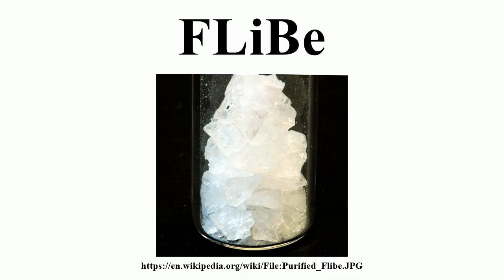This moisture plays a negative role at high temperature by converting BeF2, and to a lesser extent LiF, into an oxide or hydroxide through the reactions. And, while BeF2 is a very stable chemical compound, the formation of oxides, hydroxides, and hydrogen fluoride reduce the stability and inertness of the salt. This leads to corrosion. It's important to understand that all dissolved species in these two reactions cause the corrosion, not just the hydrogen fluoride. This is because all dissolved components alter the reduction potential or redox potential.